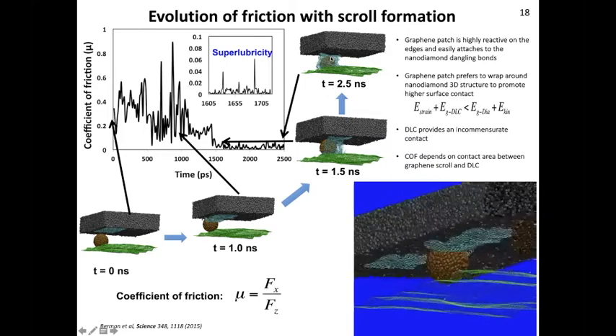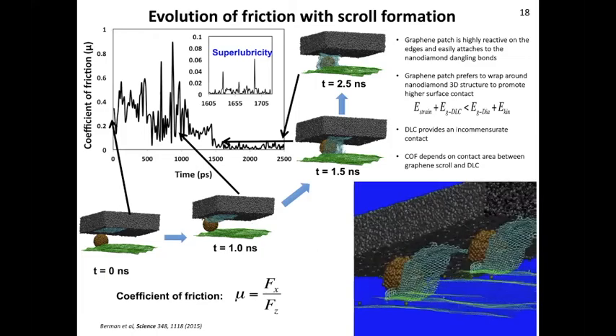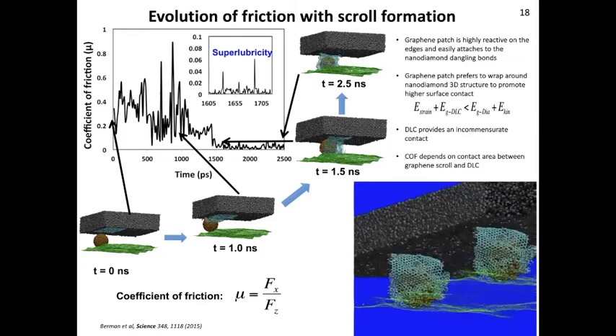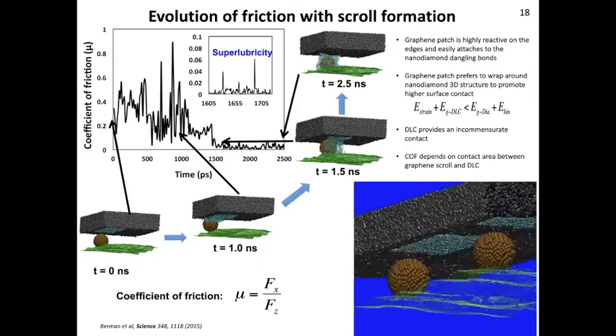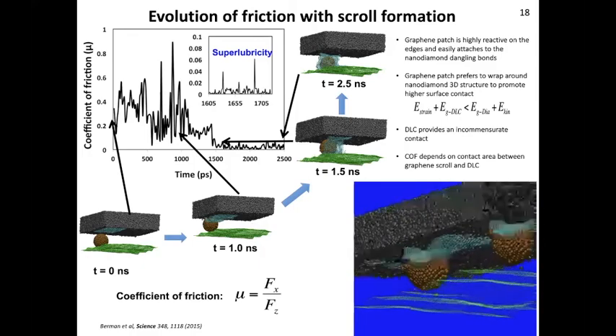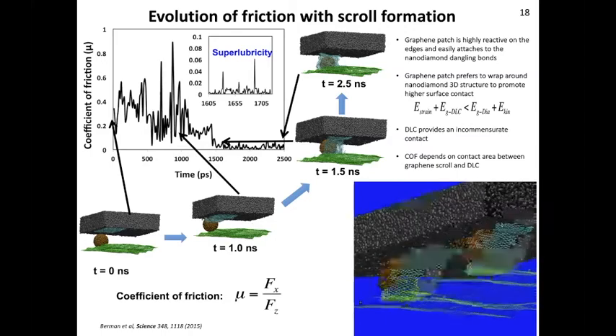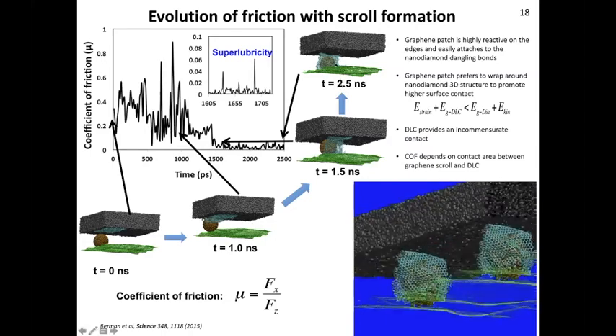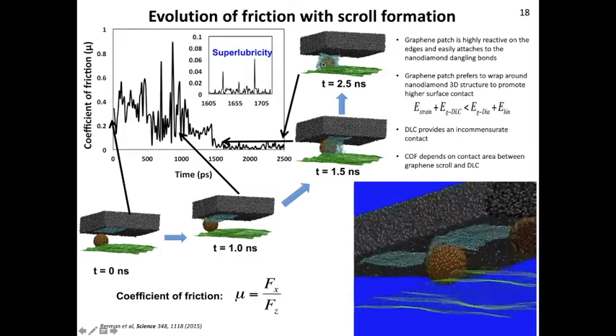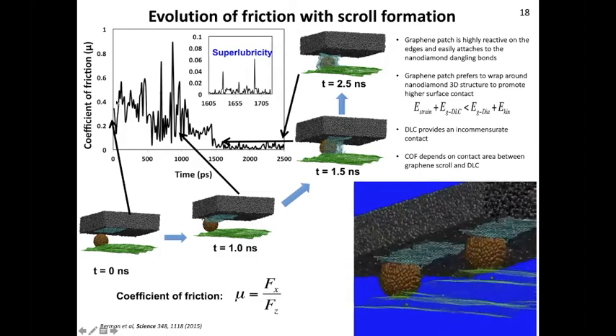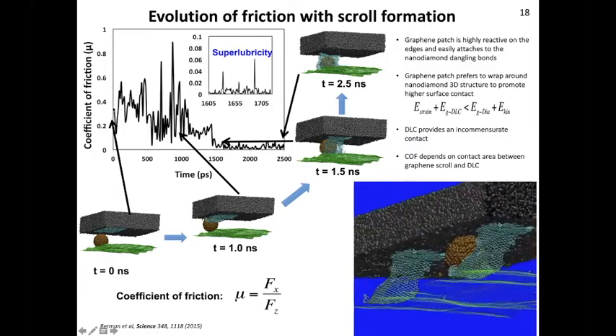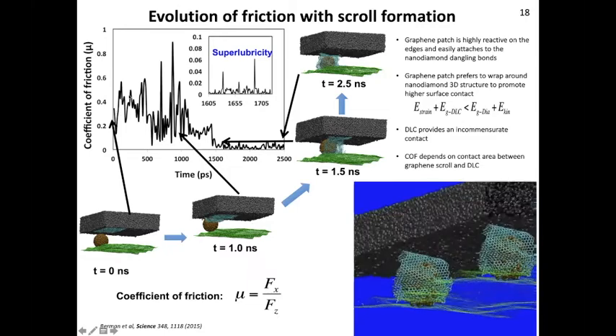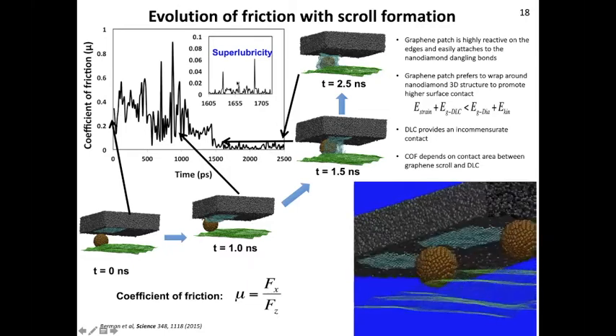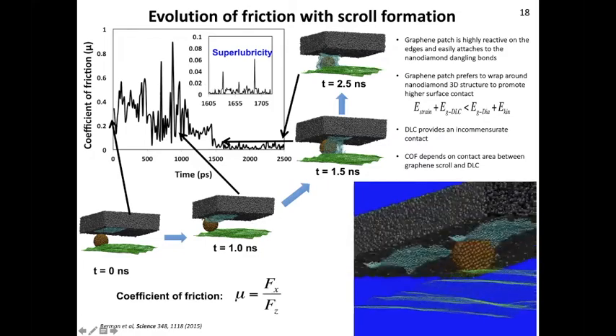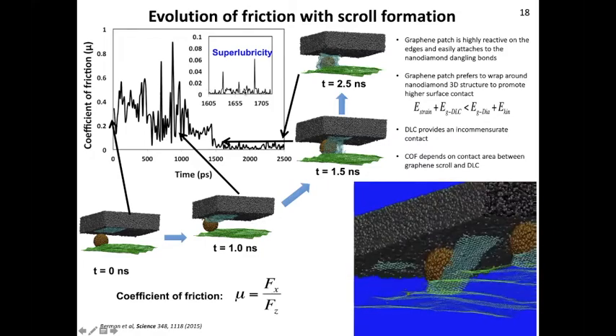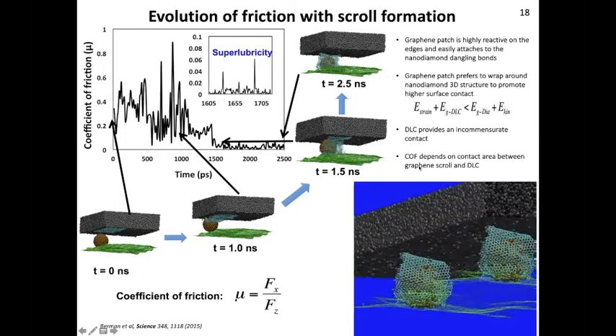Once this happens, we have completely covered any reactive sites of our diamond nanoparticle with graphene, because now our graphene shows this non-reactivity, a pretty good configuration. And we produce the separation of the surfaces, like using small ball bearings, graphene-diamond-based ball bearings. With this, our coefficient of friction, if it was initially in the higher range of around 0.2 to 0.4, immediately drops to superlubricity values. Here you can see it oscillates around 0.01. That's our superlubricity regime.